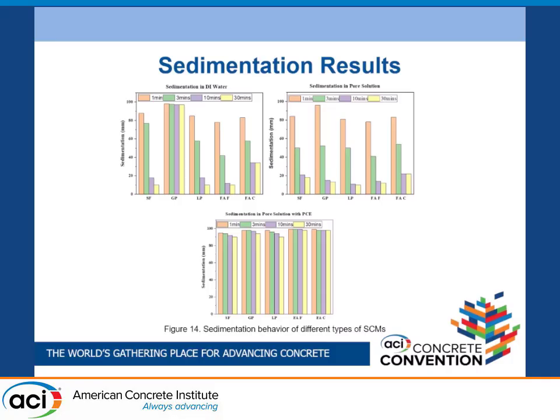When we introduce PCE, there is a significant reduction in agglomeration, and the particles disperse better. This is also proof, though a simple test, that SCMs tend to agglomerate in pore solution, and when supplemented with PCE, their agglomeration reduces.